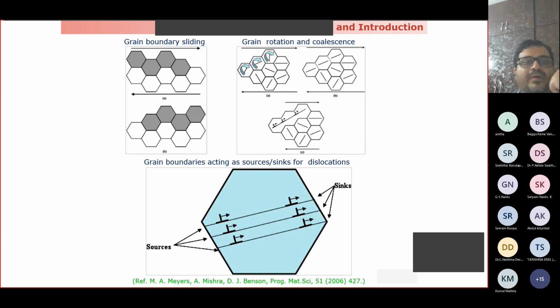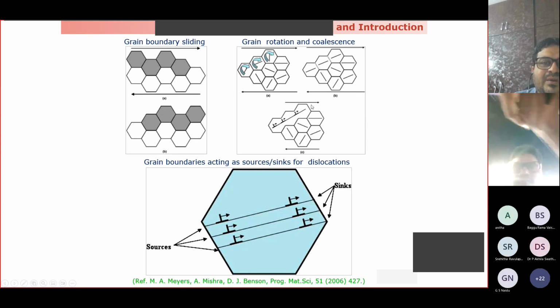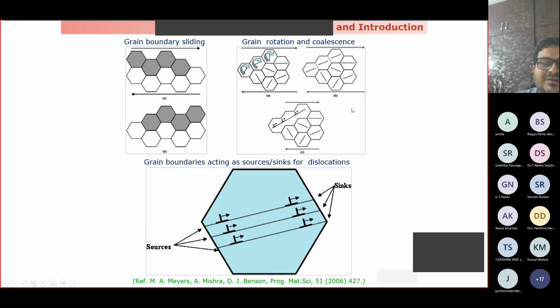So schematically, the grain boundary sliding is shown here. We have a set of grains here, another set of grains here. When stress is applied under shear mode, you see that the bottom one slides past the upper one. Likewise, grain rotation means that under the application of stress, grains get rotated and eventually boundaries get erased and you see grain growth. And these things were also observed experimentally.